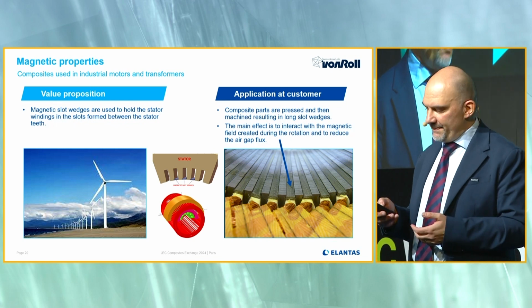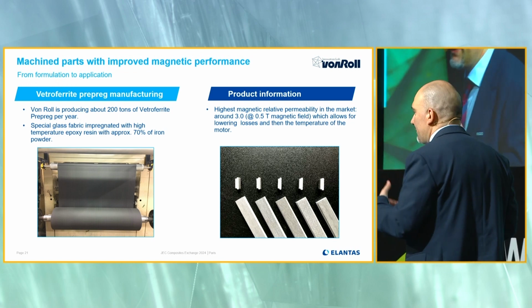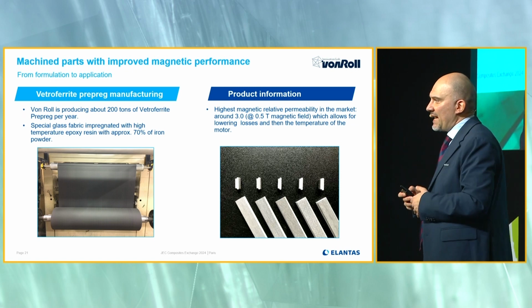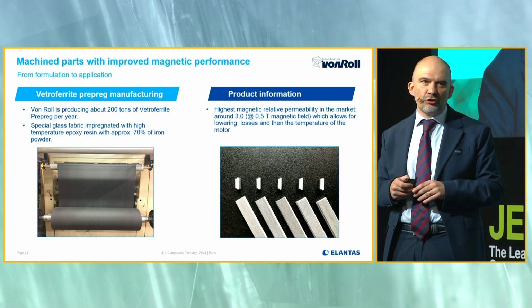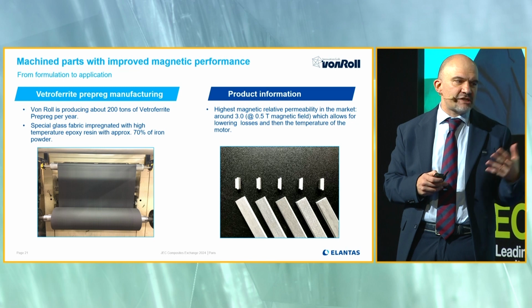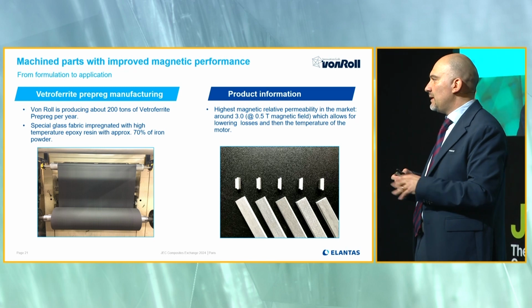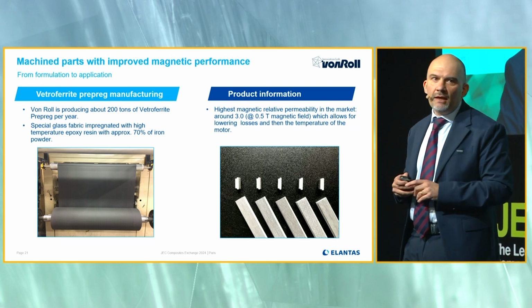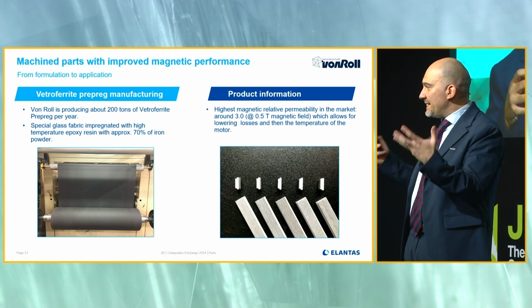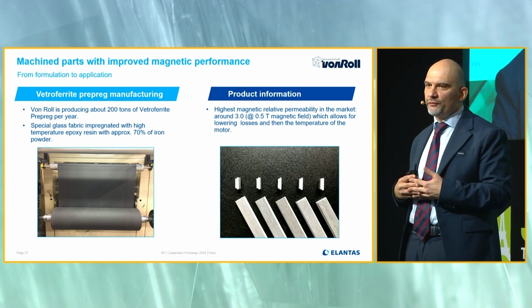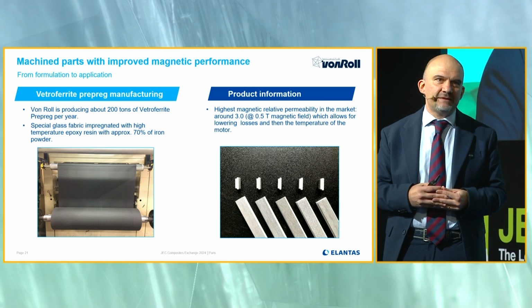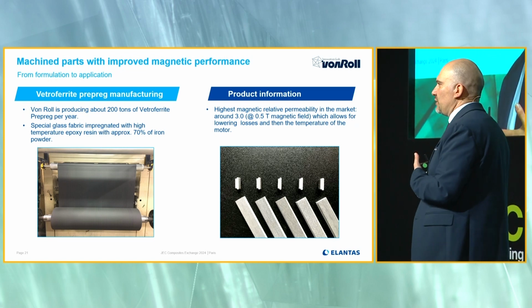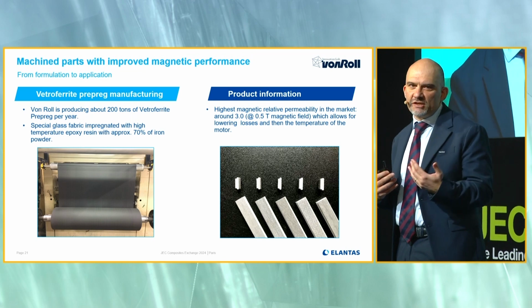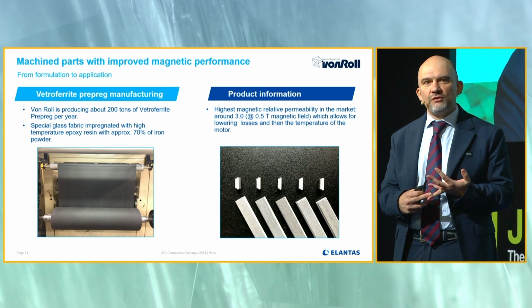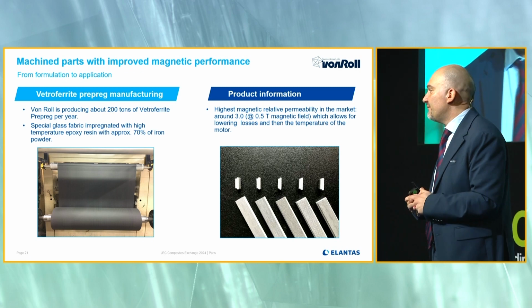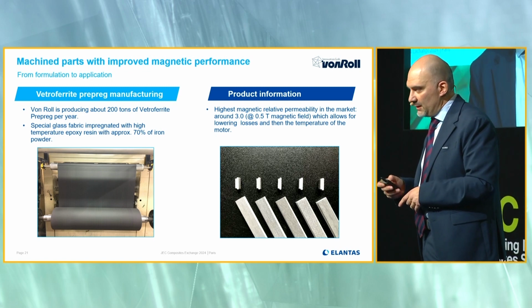How did we do this? We started from a high functionality epoxy system, with very high mechanical resistance at high temperature, and we filled this material with a high concentration of iron powder in order to increase as much as possible the relative permeability of this material, which is about 3 at 0.5 Tesla. At that level of magnetic characteristic, this product really allows to improve the efficiency of the motors by about 10%. And that, I think, was another case of how we can work on multifunctional materials to create something more sustainable, which allows reducing energy consumption and goes in the direction of a greener environment and applications for these motors.